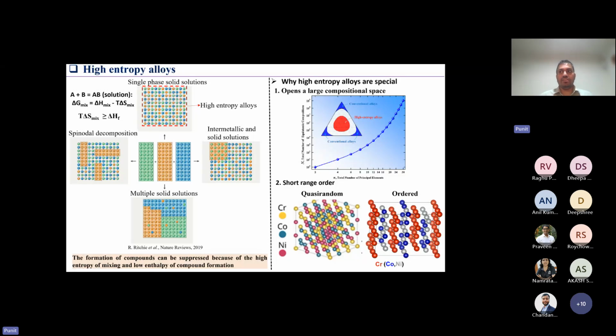stabilize the FCC phase. And the other consequence of this is that in binary alloys, the formation energy or nucleation energy of defects is constant. But in the case of high entropy alloys, depending on the extent or the type of this ordering, you can have a range of formation energies of defects, and that can have a huge consequence in terms of the deformation mechanism when you are deforming these materials. So these two examples are what I find really interesting about high entropy alloys.